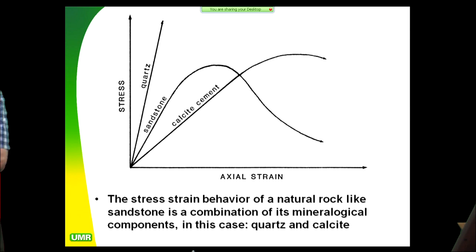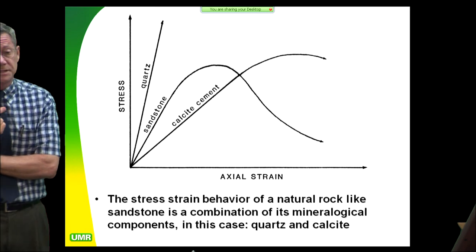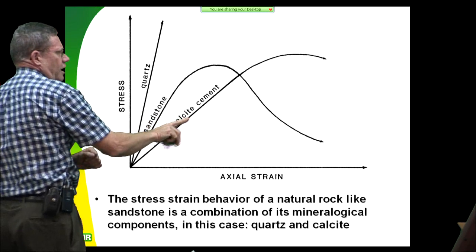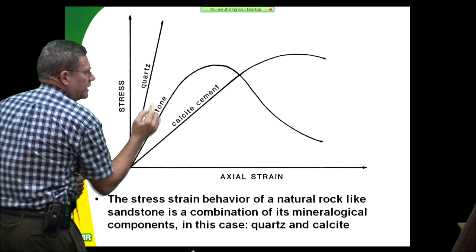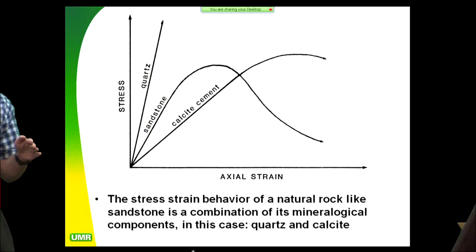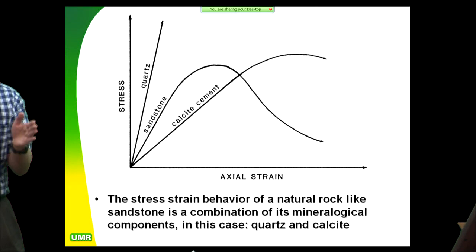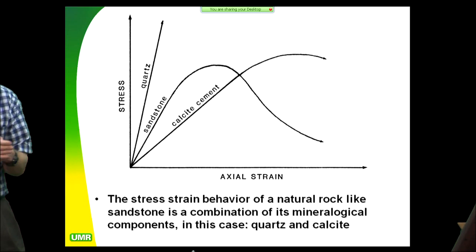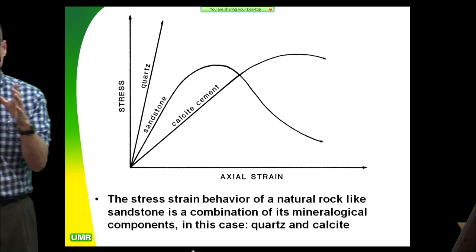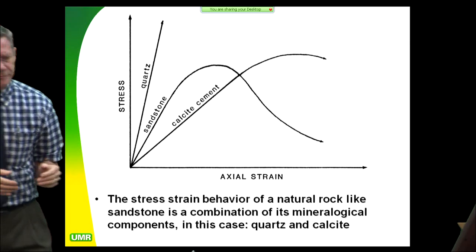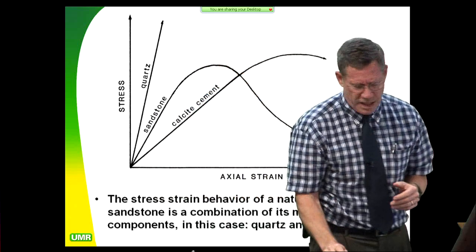Now, when you increase the strength of the matrix, like on high strength concrete, the Panama Canal was built with high strength concrete, 7,500 psi concrete. When you make this stronger, that takes this curve and brings it over here. Now you'll get much more brittle fracture at very low axial strain, and you'll break cleanly right through the aggregate. But in regular concrete, when you break it, it breaks around the aggregate if you have strong aggregate. If you don't have limestone aggregate, it'll break around the aggregate. The higher the strength of concrete, when it does break, it'll be catastrophic. It'll always scare you. And you'll see breaking right through the aggregate. And so it's much tougher stuff to deal with from a behavior point of view.